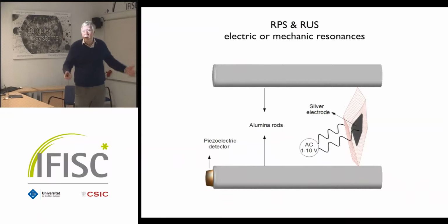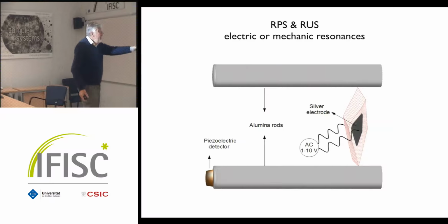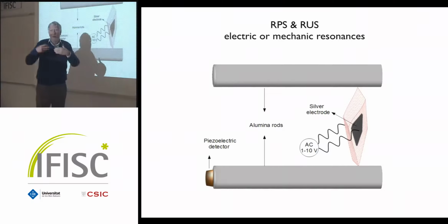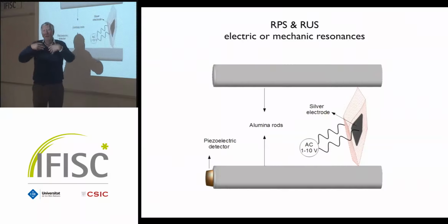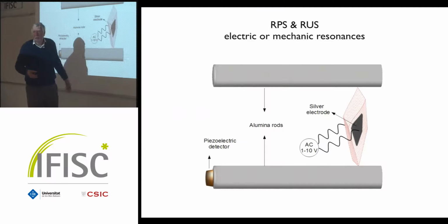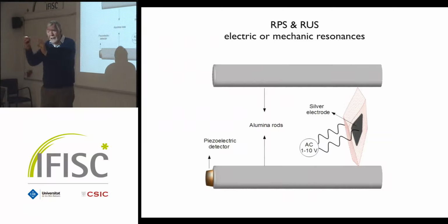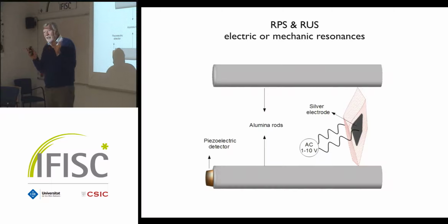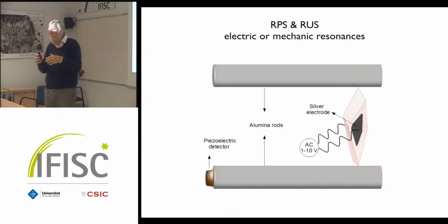And that gives you a signal on your oscilloscope. Now, if these guys swing all in phase with a nice big amplitude in resonance, then at the resonance frequency you get crackling noise. You make brrr. It really sounds like that. So when you go there, brrr, depending on where your frequency is. Okay? So that's a testing way. So you're not testing whether the material is piezoelectric as a bulk material, which would be very easy. You just squeeze it and you measure your voltage.